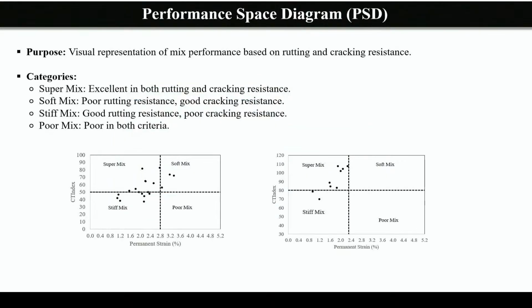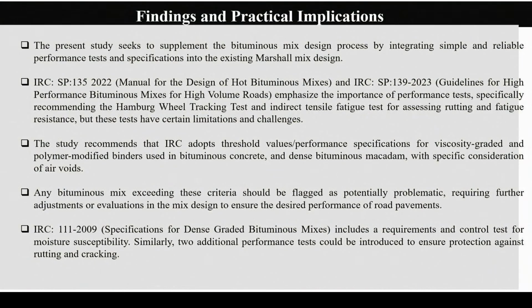And this is some performance diagram which can help us with the visual representation. So IRC 135 and 139 specifically now emphasize the importance of this performance test. However, some of the tests proposed have some limitations and challenges. So our study recommends two simple and reliable tests. Keeping the threshold value suggested in our study, any mixture having more than the threshold value can be marked as problematic, and can be re-evaluated or redesigned.